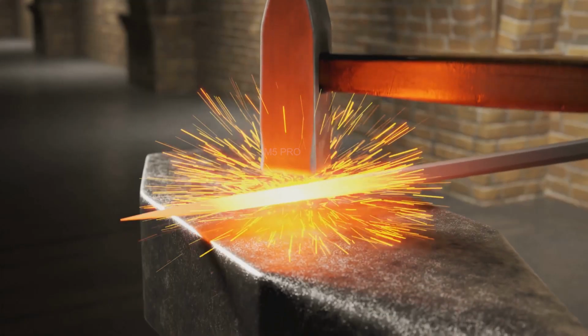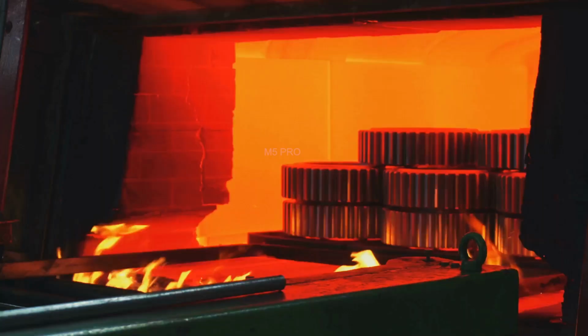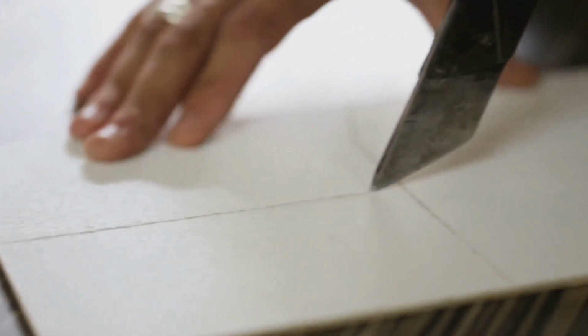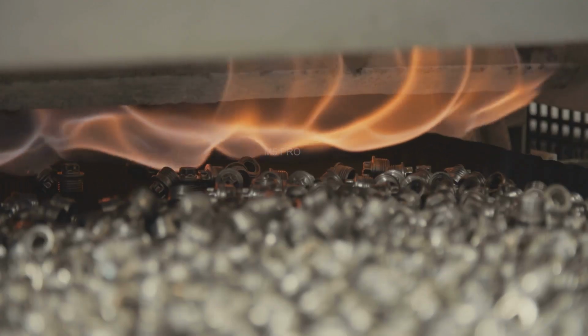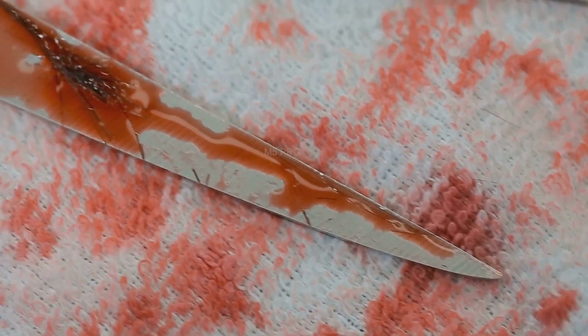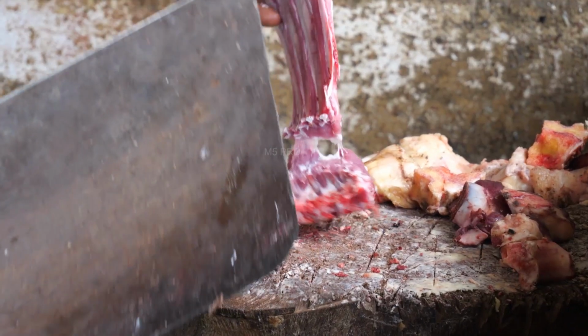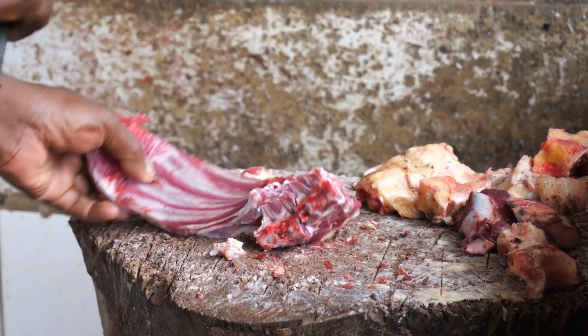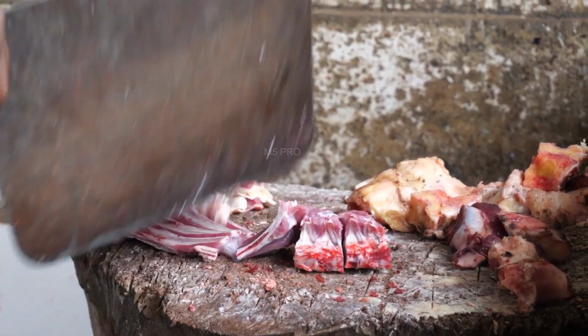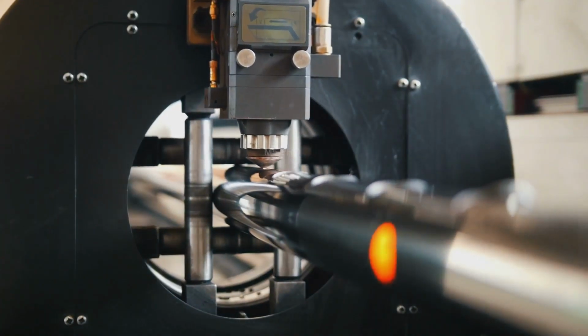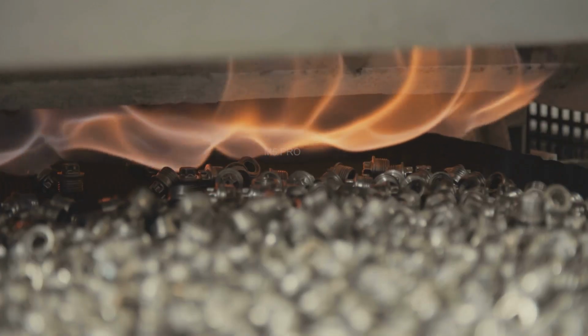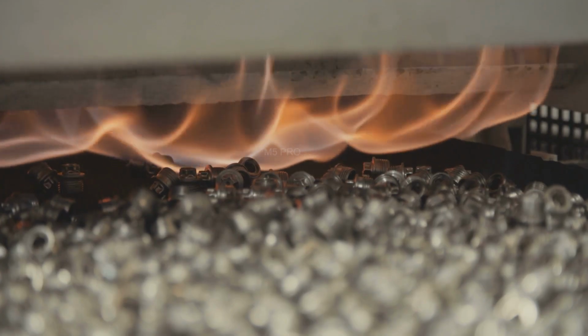After the quench, the blade is completely transformed. It is now glass hard. If you were to drop it on the concrete floor, it would likely shatter into several pieces. At this stage, it can hold an incredibly sharp edge, but it has zero toughness. It's too brittle to be a useful tool. A single hard chop against a bone would cause the edge to chip away like a piece of flint. We have successfully achieved maximum hardness, but in doing so, we have sacrificed all durability.